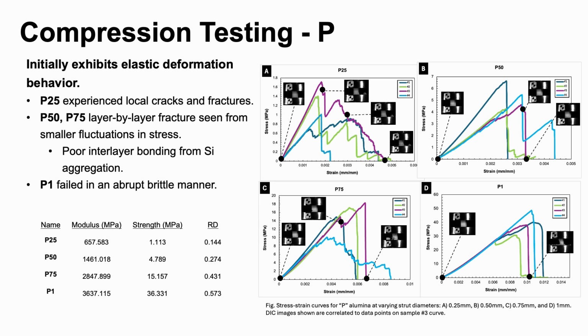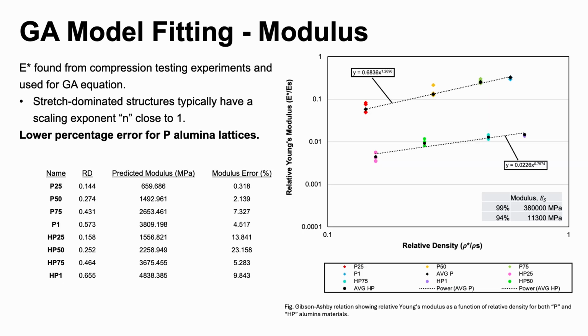The fluctuation in stress may also be a result from silicon conglomerates, as seen in the XRF analysis, that caused premature failure due to poor interlayer adhesion. P1 shows a more distinct stress strain curve with a linear region and a sudden stress drop. So once we calculated the lattice modulus, we were able to start fitting our experimental data to the model.